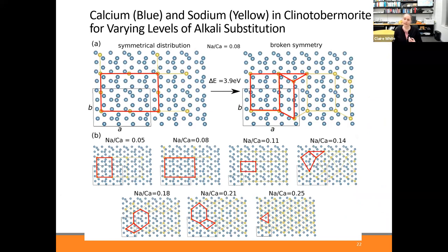We can look at the formation energies of these structures with respect to the original clinotobermorite structure. I'm going to show that on the next slide, but what's shown on this page is that you can put the sodium atoms in different locations, so you can choose in the interlayer region essentially what substitution to do. That's what we had to do here.